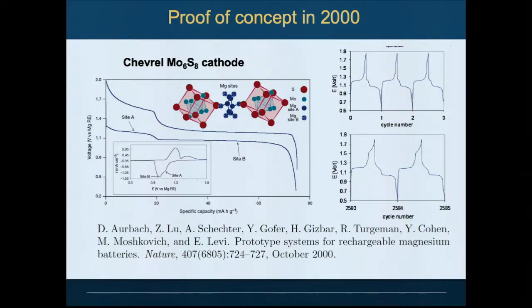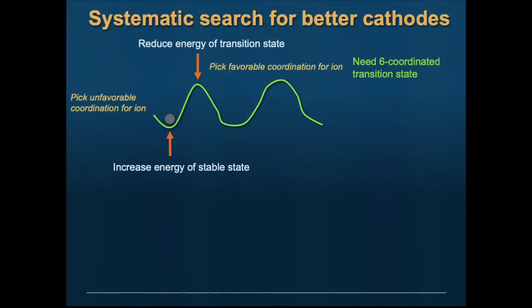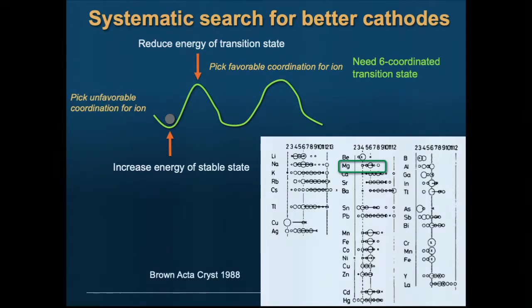The problem is that since 2000, we haven't exactly made a lot of progress. We made a little bit of progress, again, by thinking logically about the diffusion. And this is the story on which I'll end: the answer for making a good magnesium diffuser turned out to be remarkably simple. Again, if you think of this landscape, you want to get this down and this up. If you want to move magnesium, you want the stable site to have unfavorable coordination, and the activated state to have more favorable coordination. The typical coordination environments for magnesium are mostly 6-fold. Magnesium is usually preferred as 6-fold, and occasionally goes 4-fold. So what do you want to make? You want a material where this is 4-fold and this is higher, like 6-fold.